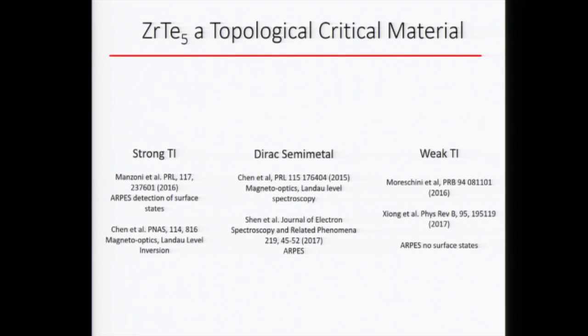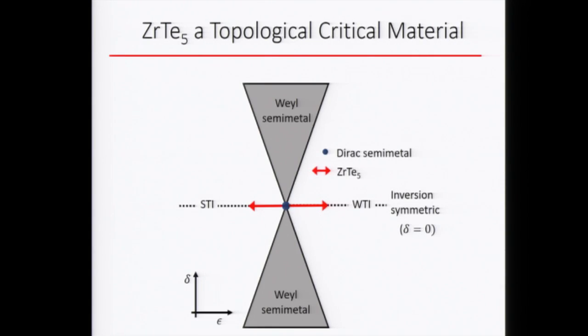And one of the difficulties is that you're getting very close to this critical point. It could be here, it could be there, and most likely it depends on how you grow the material, how you glue down the material, how you strain the materials.